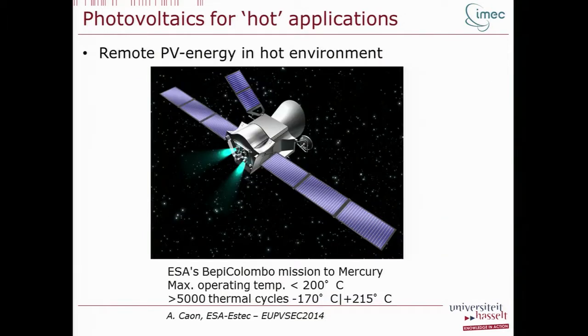If we now go to the other extreme, it was presented very recently at a PV conference in Amsterdam by people of ESA ESTEC. Since organic-based photovoltaics are increasing very fast in efficiency, perhaps applications in the aerospace field can come as a possible application. Here I just give you the idea of what the conditions are. So for the BepiColombo mission to Mercury, the solar cells have to have a maximum operating temperature below 200 degrees Celsius and thermal cycles between minus 170 and plus 215 degrees Celsius. So also these extreme applications can have extreme conditions.